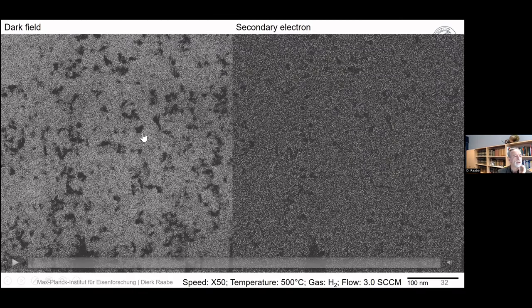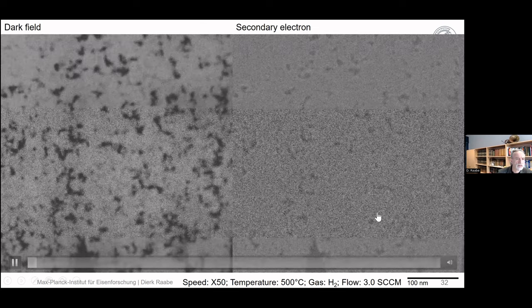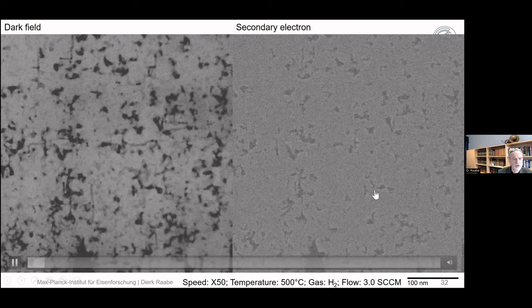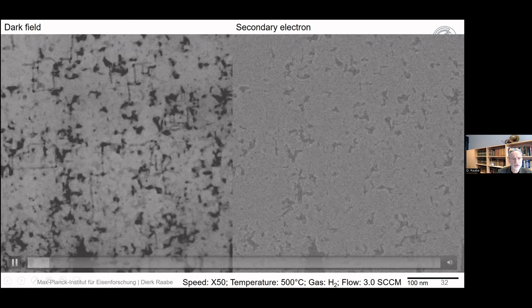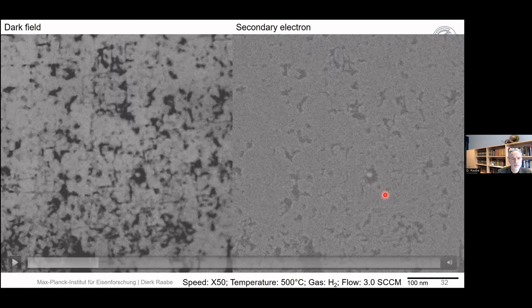This is now done in a high resolution scanning transmission electron microscope under full hydrogen flooding. That means the entire column of the microscope is under hydrogen conditions. And you see, when you look closely on the right hand side, maybe if I stop the movie, you can see this little sphere appearing in a bright color. And also the rims here are the first iron nucleation sites that we directly observe, so to say, in such a reactor in the electron microscope.